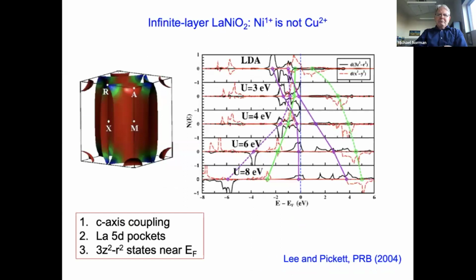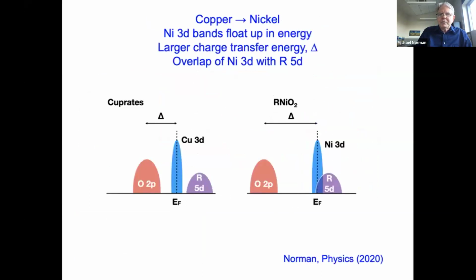So Warren Pickett and a student pointed out back in 2004, though, that lanthanum nickel O2 is not as close to copper 2 plus as you might think. And in particular, what they noticed is because of the infinite layer structure, the c-axis coupling is much stronger than what you see in a typical cuprate. Plus, you have pockets formed from the 5d orbitals of the lanthanum site, and then the 3z squared minus r squared states are closer to the Fermi energy than in the cuprates. And so this makes these nickelates a little bit different than cuprates.